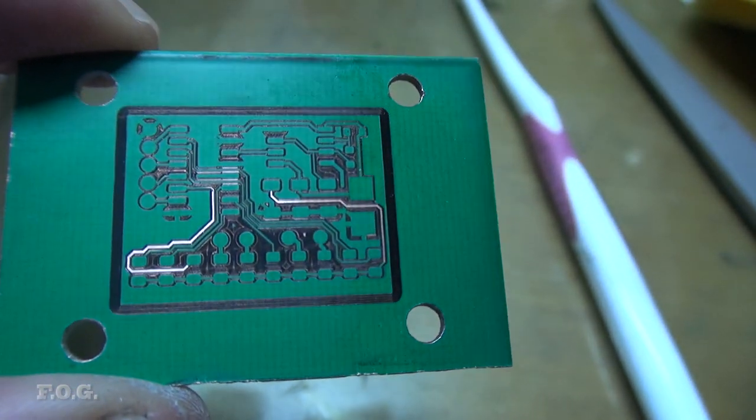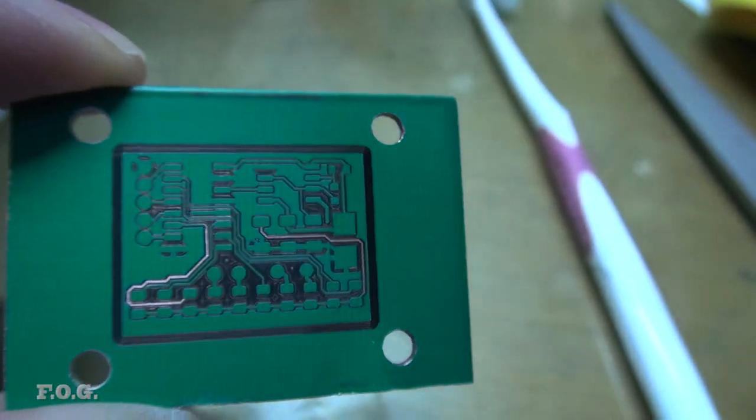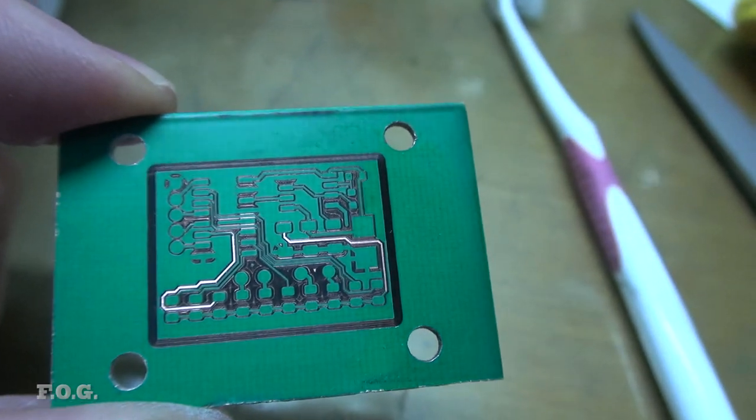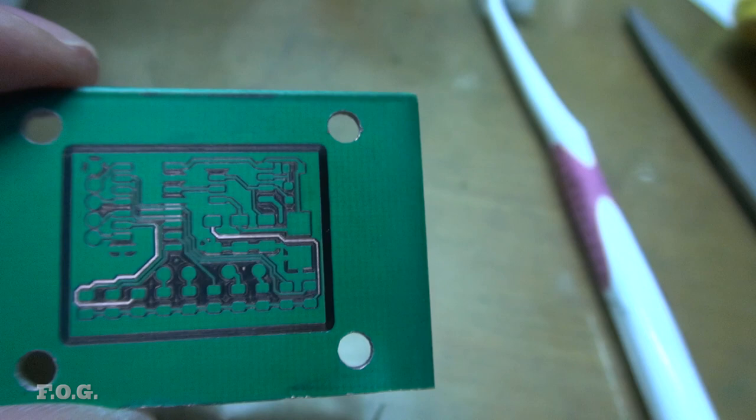So after cleaning you can clearly see that a couple of those tracks on this side at least have been blown off. So that means that I'm just pushing it too hard. It's possible also that I'm just pushing a little bit too much temperature. I've got the laser running a little bit too hot for this style.